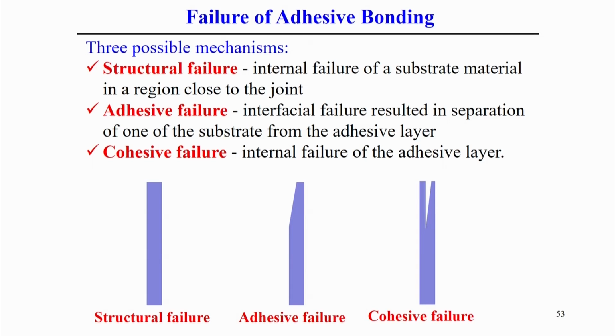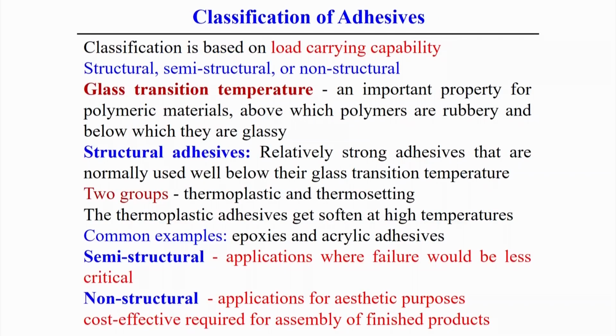If you see the adhesive failure figure, here you can see a small component of the adhesive has disappeared. So, actually failure happens near the substrate material and one layer is absent in this case. That is the typical mode called adhesive failure. Cohesive failure is when the internal failure occurs in the adhesive layer. The failure is completely within the adhesive volume itself, and that is called cohesive failure. So, these are the three different types of adhesive failure modes we observe in adhesive bonding.